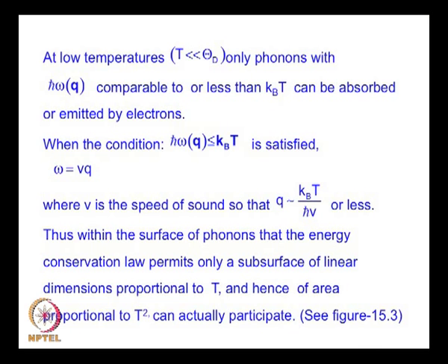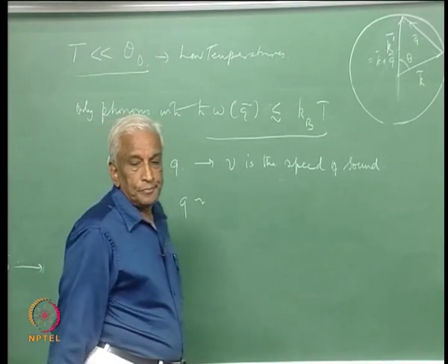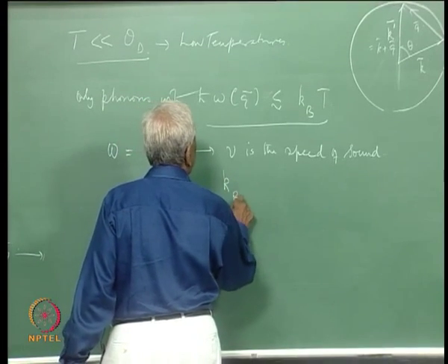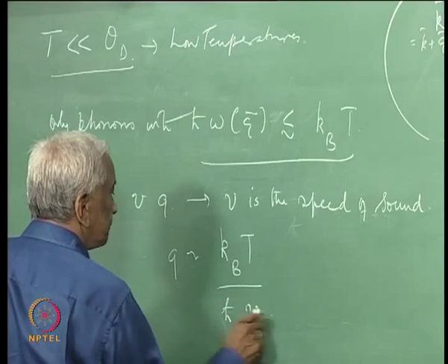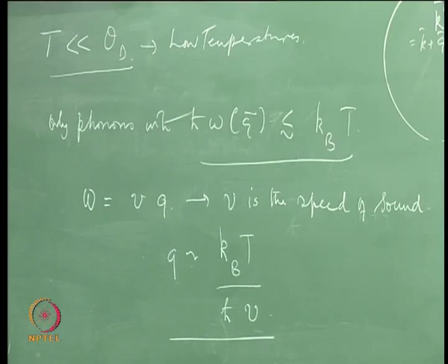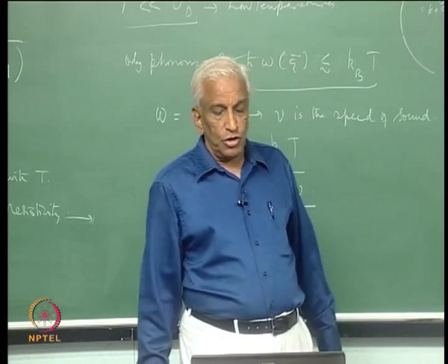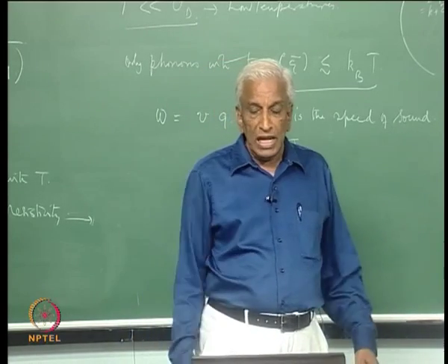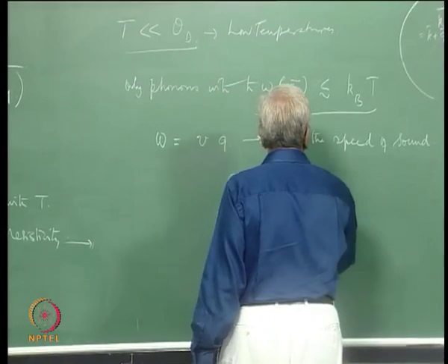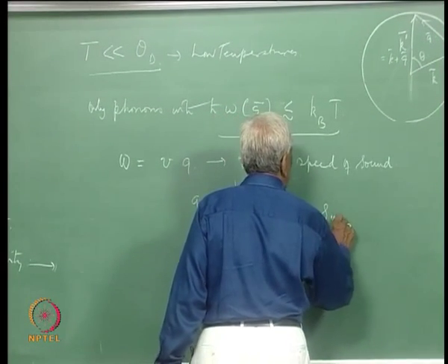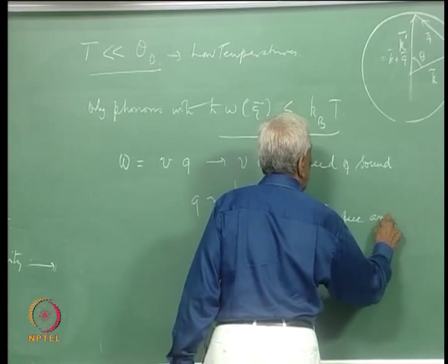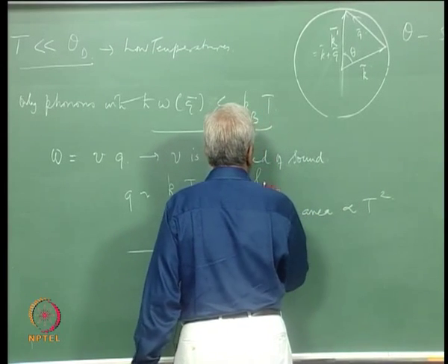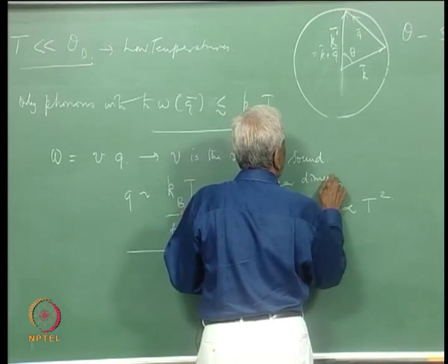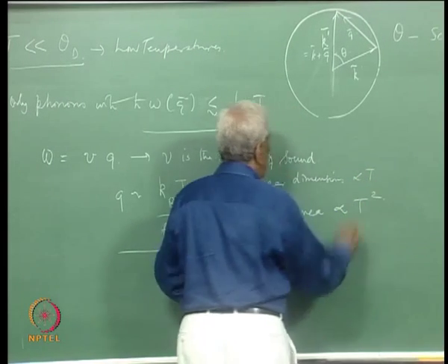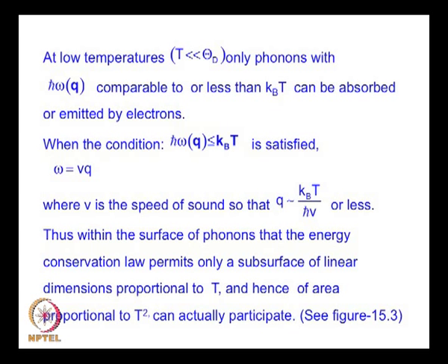So, that Q is of the order of kBT by h cross V. That is the condition for the phonon wave vector. So, only within the surface of phonons that the energy conservation law permits, only a subsurface of linear dimensions proportional to T, and therefore surface area proportional to T square, can actually participate.